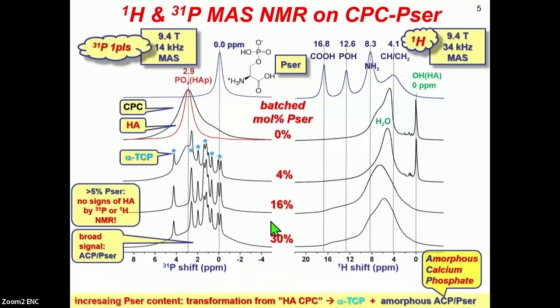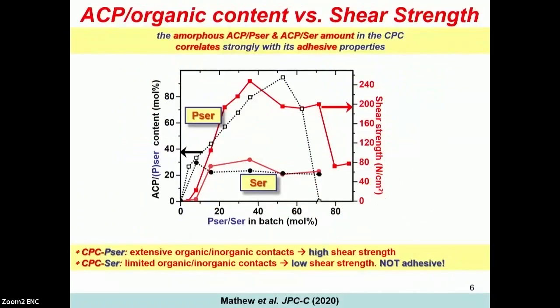And this component is largely responsible for the bone adhesive properties. We have found very good correlations between the amount of the ACP PSER phase and the shear strength experimentally observed from the cements if you take 2 cubes of either bone or steel and glue them together. And in the plot you see here,